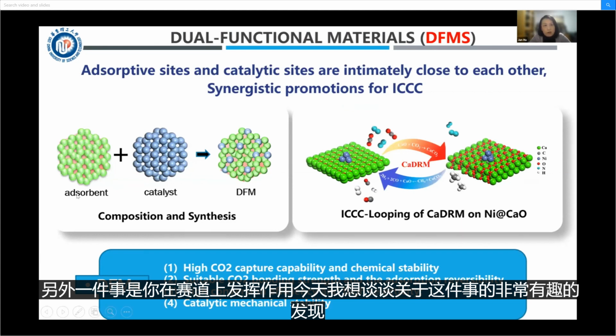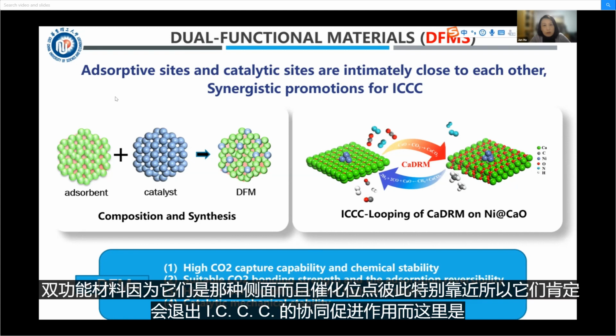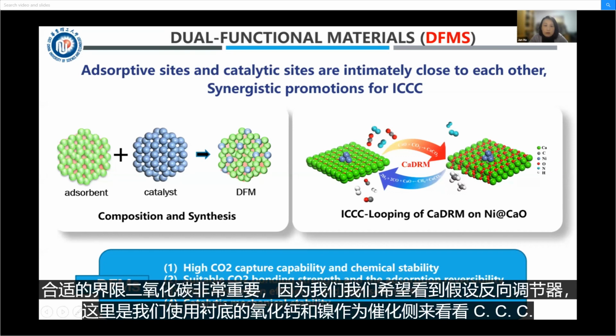Another thing is the dual functional materials. Today I'd like to talk about some very interesting findings about the dual functional materials. Because the adsorptive sites and the catalytic sites are intimately close to each other, they surely will exert synergistic promotion for the ICCC. Here, suitable bonding of CO2 is very important, because we want to see the adsorption reversibility. Here we use calcium oxide as the substrate and nickel as the catalytic sites to see the ICCC looping performance.